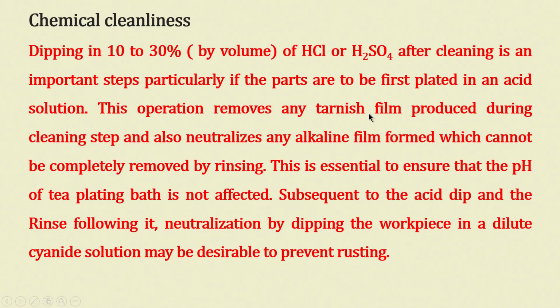HCl is fairly good enough to clean most of the dirt and other things for chemical cleanliness. H2SO4 also should be approximately 10 to 30%. So, after cleaning, the parts are removed and checked for tarnish again. If the tarnish is gone, then the next step can be just neutralizing and then going ahead with electroplating.